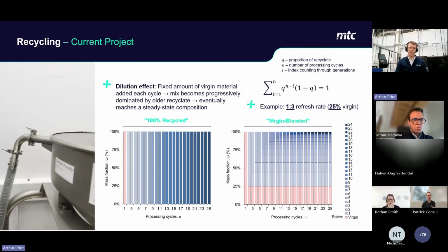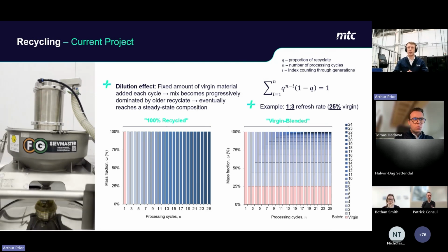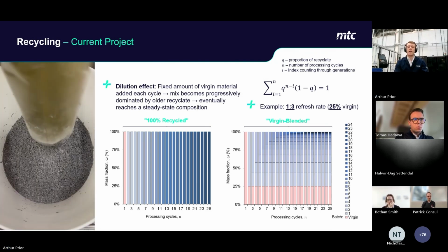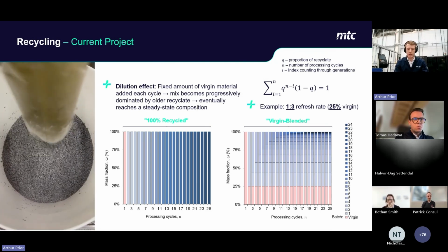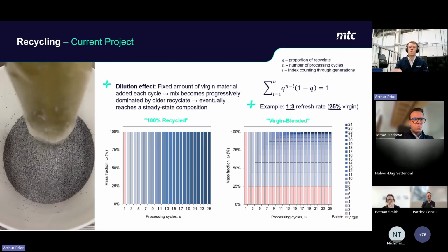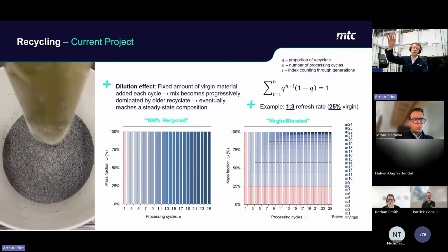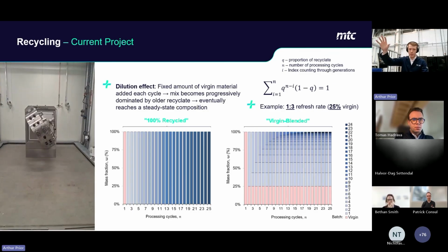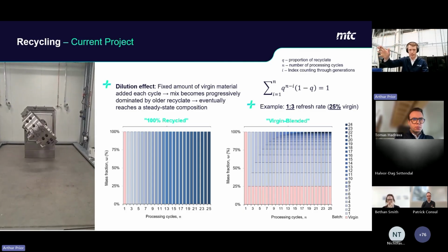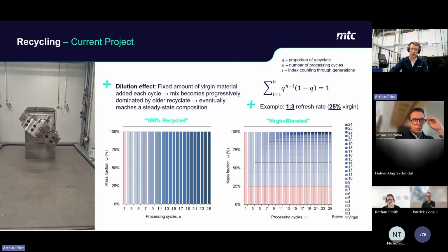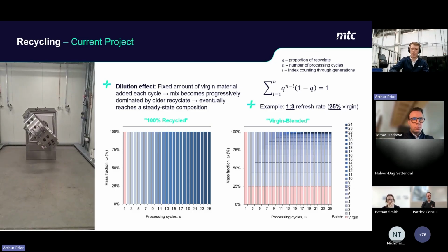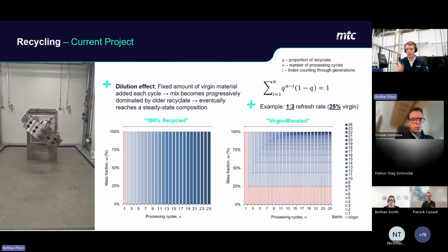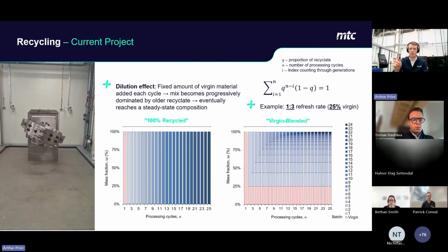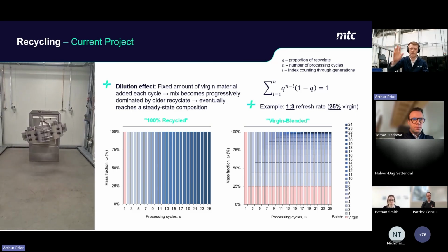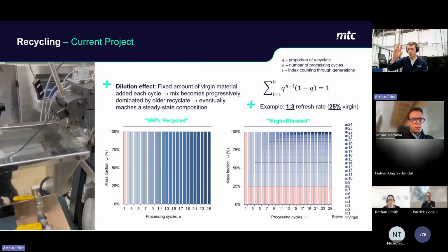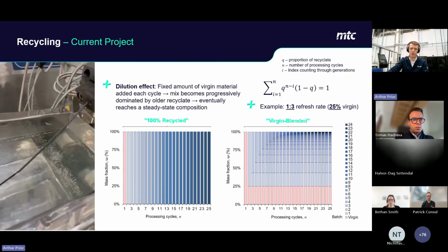So the important concept here is the dilution effect. So if you add a fixed amount of virgin material each cycle, then the overall composition will gradually become dominated by older generations until it reaches a steady state. So the example shown here is a 1:3 refresh ratio, so 25% virgin material. And as you can see on the right-hand side, this will reach an equilibrium after roughly 25 processing cycles.